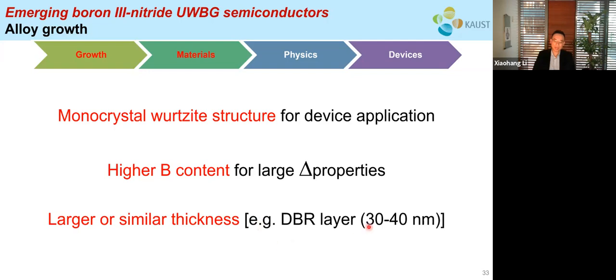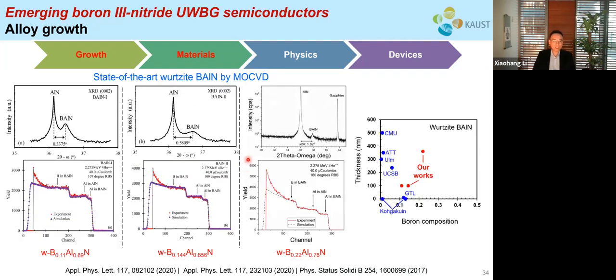For example, a DBR layer has a thickness of about 30 to 40 nanometers, and we have to realize a thickness higher than or equal to that. So, without elaborating on the growth details, we have demonstrated state-of-the-art wurtzite boron aluminum nitride materials. Here we have the XRD and RBS spectra, for both the crystal quality and composition characterization. On the right, we have the thickness versus boron composition of our results, benchmarked against results from other groups. As I mentioned earlier, the higher the thickness and the larger the boron composition, the better, right?